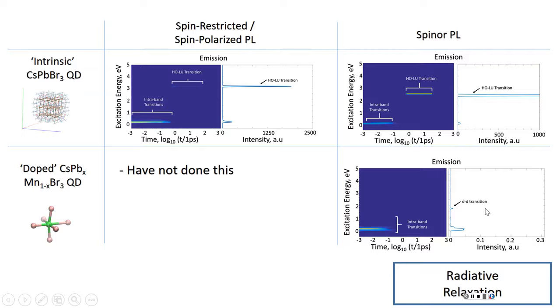But don't you say, I remember from your poster, one of the main results was that you will have emission from this state only if you include spin orbit. Yes. And this is with spin orbit. This one here is spin orbit, yes. So it is small but not zero. If you don't have spin orbit, then it's completely dark. Right, and with spin orbit, you have weak oscillator strength. I was going to say, in experiment, they see that this peak here should be the same order of magnitude as this peak. But in experiments, they probably don't have a single manganese impurity.